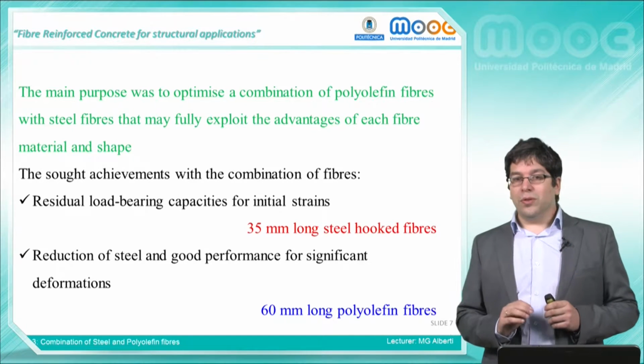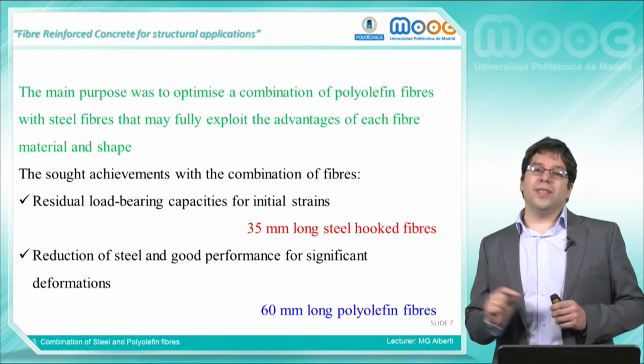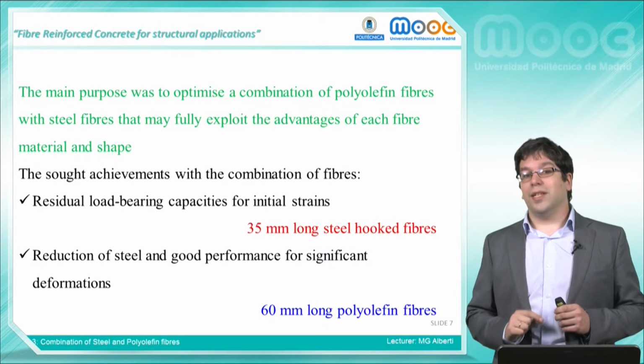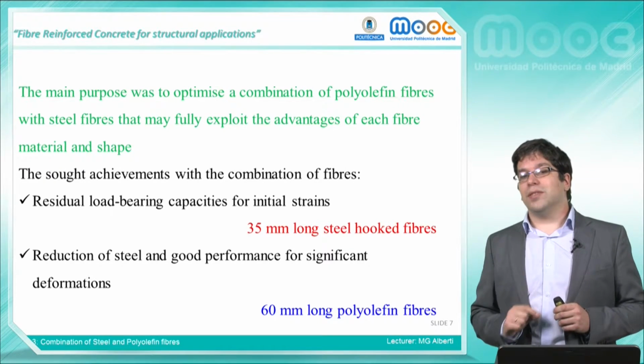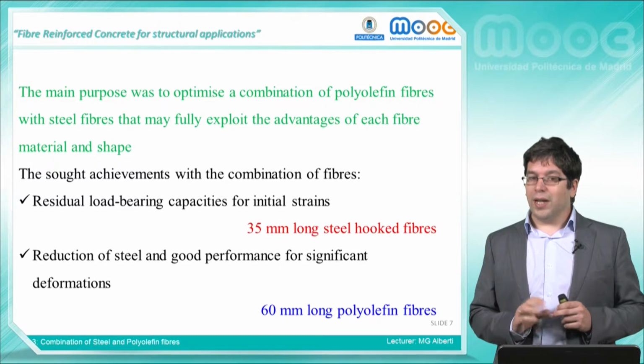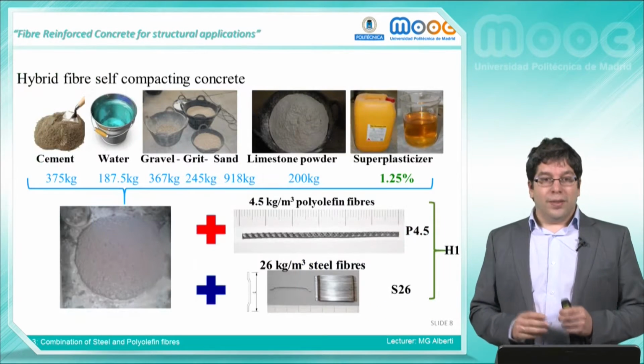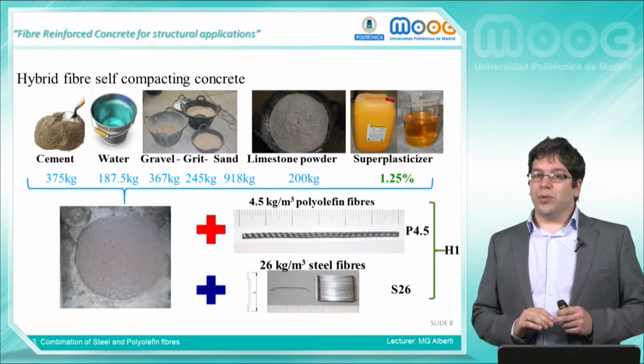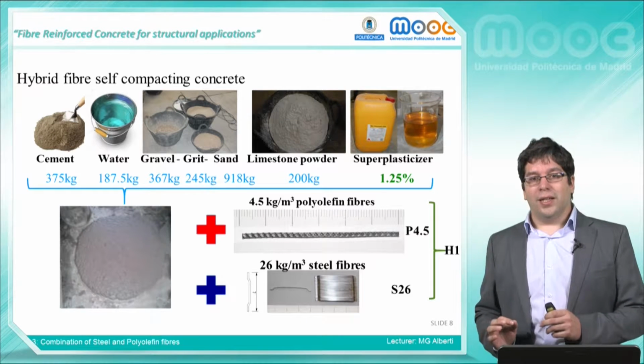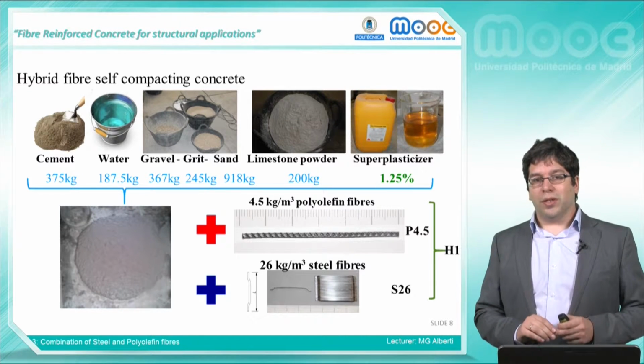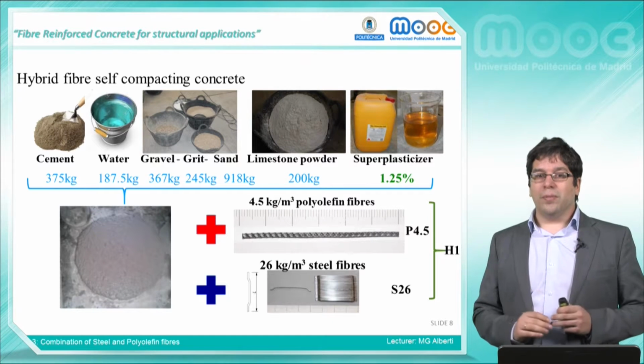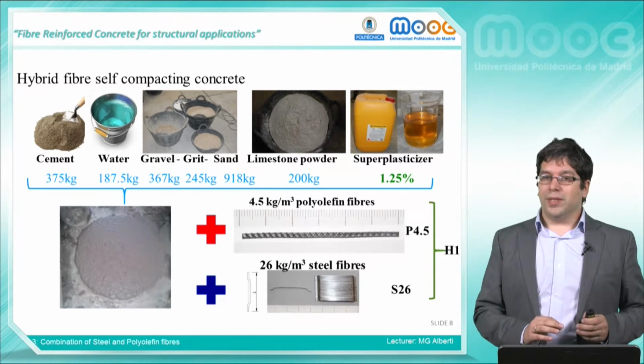In order to do so, short hooked-end steel fibers were chosen for the initial strains and 60 mm long polyolefin fibers to improve higher deformations. The individual dosages of fibers were also produced on the same mix design. Therefore, the properties could be compared with results of the mixture with both types of fibers.